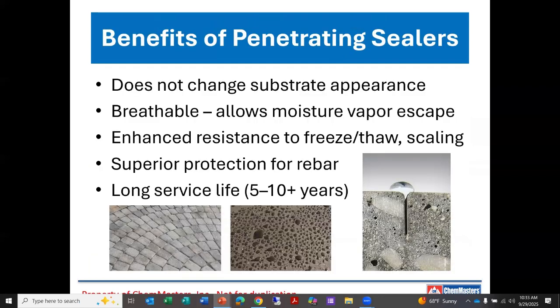Again, these products do not change the substrate appearance. They're highly breathable. They do not have a film forming component. Therefore, they allow any excess moisture in the concrete to escape readily. Enhanced resistance to freeze-thaw cycling and scaling, superior protection for the rebar, and depending on the application, whether it's vertical, horizontal, whether it sees traffic, whether it sees de-icing chemicals, you could see service lives of 5 to 10 years or so. And as you can see particularly with the picture on the right, that is a saw cut with a drop of water on top, and you can see how effective they are at keeping water out of concrete, even when there's a substantial means of ingress, which is that saw cut.